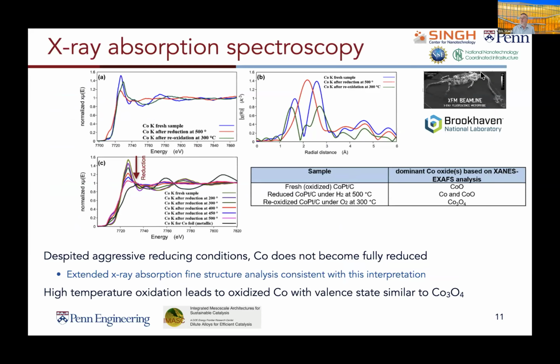We then use the X-ray fluorescence microscope beamline at Brookhaven National Laboratory. This beamline has the ability to focus the probe down to around a couple of microns. We tended to use around a 10 micron focus. What that allows us to do is to look as we reduce the sample in hydrogen at 500 degrees Celsius, and then go back and oxidize it again at 300 degrees Celsius.